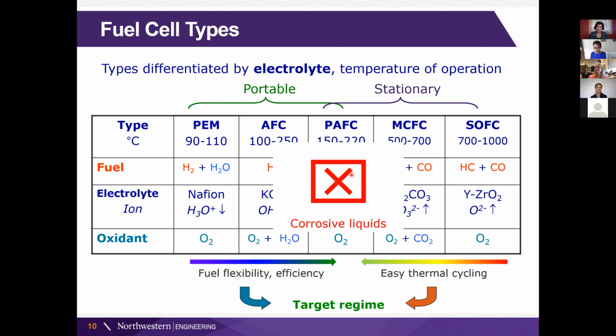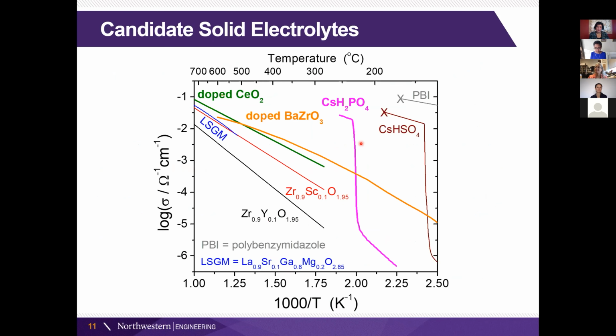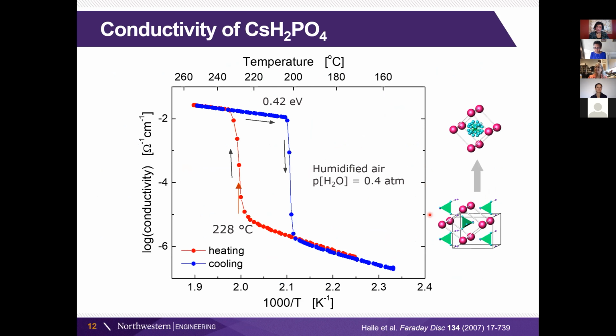And so there is this target regime of developing solid electrolytes, solid ionic conductors that operate in this intermediate temperature regime. There are some, and in my laboratory, we work with all 3 of these materials that skate at the top of the conductivity in these different temperature regimes. What I'm going to tell you about is what we've done with this particular material, cesium dihydrogen phosphate, which is a proton conductor. The nature of this material is such that we have these phosphate groups and cesium ions that form a monoclinic structure at low temperature. With just a little bit of heating to a high temperature phase where we have a transition, that material transforms to something that looks close to a cubic structure, this cubic phase. It's a cesium chloride structure type.